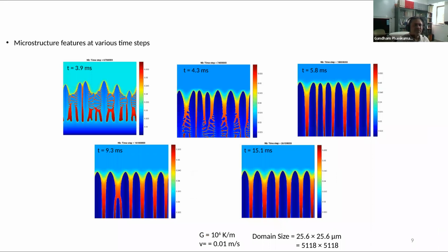Okay, and then we can also do a time evolution of what's happening because this is done in a computer. So to visualize what is happening during solidification at a small scale, you can actually do it in the computer. And so as the time increases, you see that the pattern formation is changing for a particular gradient and velocity. Which means that the time evolution of a pattern formation can also be understood, which then can lead to us explaining what happens at the beginning and at the end of a track, for example.